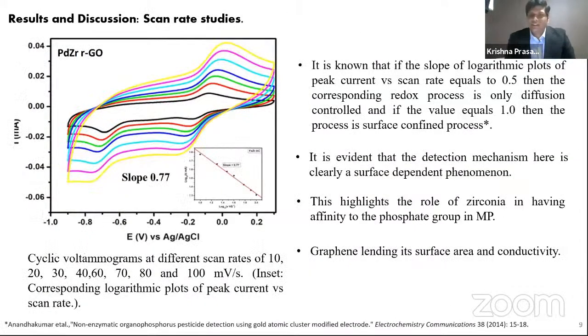Further, it is important to know whether the reaction which is happening is a diffusion-controlled process or a surface-driven process. To study that, we have done the scan rate studies and have plotted the logarithmic plots of peak currents versus the scan rate. It is known that if the slope of this plot is 0.5, then the corresponding redox process is a diffusion-controlled one. And if it equals 1, or if it is more than 0.5 and closer to 1, then it is a surface-confined process. In this particular experiment, we have found the slope to be around 0.77. It is evident from the slope that the detection mechanism is clearly a surface-dependent phenomenon. This particular experiment highlights the role of zirconia and graphene in the composite material, which is helpful in the detection of methyl parathion.